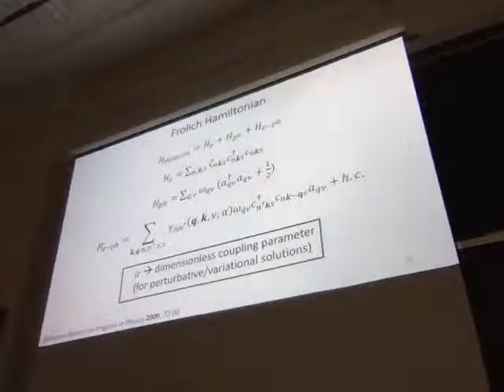And so the Hamiltonian for polarons in general, if you want to think about how to describe the electronic structure of these, is the Frohlich Hamiltonian. It was the first Hamiltonian used to describe these, back in the 1950s, in second quantization form. Basically it's made up of three parts. You have your on-site electronic states, you have your independent phonon modes, and you have the cross term, the electron-phonon coupling. If you put the charge in, it interacts with the nuclei, so that gives this cross term.